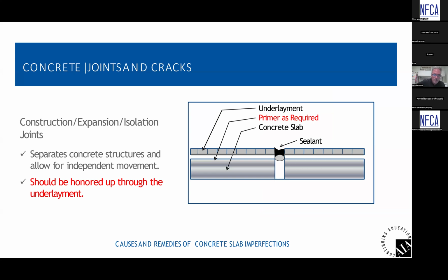And Seth, that tendency to curl and relax dissipates as the slab dries. Is that right? It does. It certainly does. If you get dry concrete, you've got stable concrete, and then you're able to grind the curl flat without worry about a change of shape afterwards. Right. But you're into moisture testing and concrete evaluation as well. Yeah.